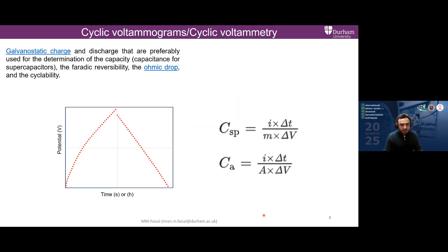Coming towards the GCD analysis, GCD is somehow a similar trend. In cyclic voltammogram, we provide potential at a specific scan rate. In GCD, what we do is we provide a specific current, and we set a potential for any electrode material or any cell, which could be in 3 electrode or 2 electrode, and then that specific current reaches up to that potential, and then starts discharging, and then again reaches the zero potential from which it started. So this is a whole cycle of charging an electrode material and then discharging an electrode material.